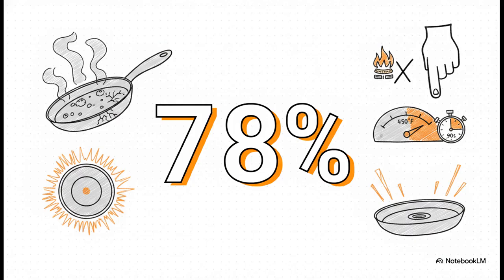Now, it's not the pan's fault at all. It's just because users carry over their old gas stove habits. They just blast the heat to high, and because induction is so insanely fast and efficient, they blow right past the 450-degree Fahrenheit breakdown limit of the PTFE coating in under 90 seconds. You literally have to modulate your power on induction.